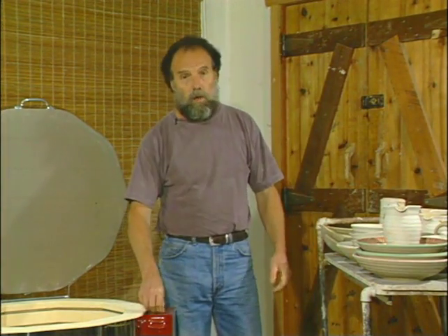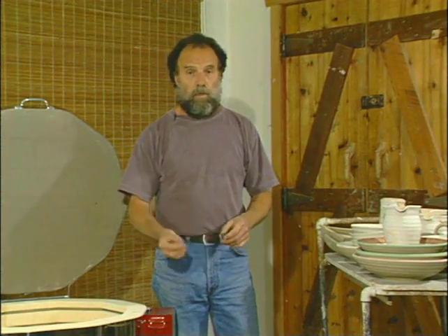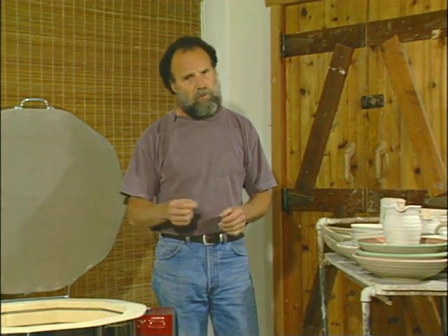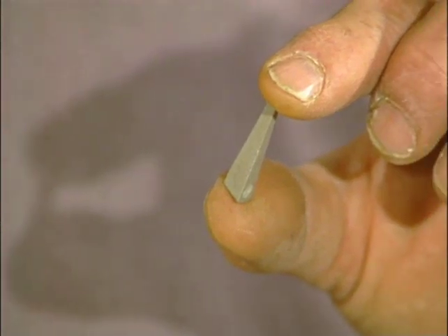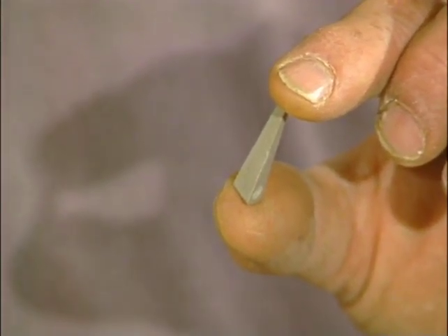Okay, before we load the bisque kiln, the first thing we've got to do is arm the kiln sitter with this indicator cone for bisque firing. Cones are used to measure temperature in ceramic applications. They're formulated to measure any temperature throughout the ceramic range. This particular one is a cone 010, and that's an appropriate temperature for a bisque firing of earthenware clay.